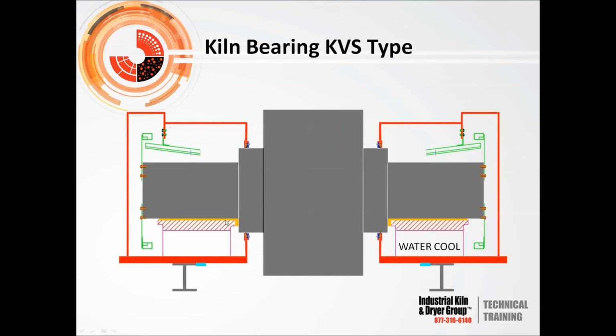And same thing applies to this design. This is the KVS design. They shrink a cast iron ring onto the journal, and that thrust load is taken off that flange on the bushing. Same deal. You got to look in there and see whether you got a gap. You know, if it's thrusting downhill, you'll see like 3/16 of an inch gap up here on the uphill bushing face, and it'll be tight down on the bottom. And that tells you which way you're thrusting, but it doesn't really tell you how much you're thrusting.